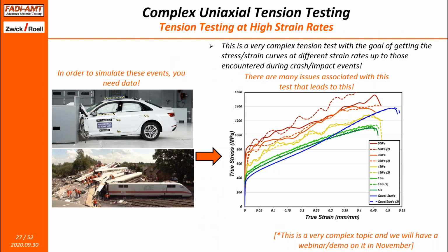The critical area of high strain rate testing, or testing at high speeds and high strain rates. It's a simple fact. If you want to simulate events like crash, impact, then you need data. And that data is simply tension testing data at different speeds. And the typical scenario is that we have so many issues associated with this type of test that typically you have a nice material behavior at low strain rates, as shown on the right-hand side, which is the blue curve. And every time you increase the speed, you get more and more trouble.